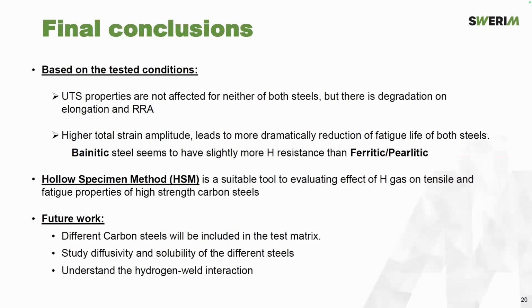So as a conclusion, we could say that in these tested parameters, UTS properties are not affected, but we saw a reduction in elongation and reduction of area in hydrogen environment. For the fatigue test, at higher strain amplitude we see a more dramatic effect in the reduction of fatigue life. It seems that the bainitic steel still behaves a little bit better, but there is still a detrimental effect. Then we could say that the hollow specimen method is, at least for the moment, suitable to evaluate the effect of hydrogen gas in this kind of material.